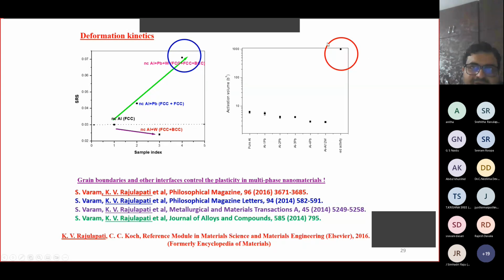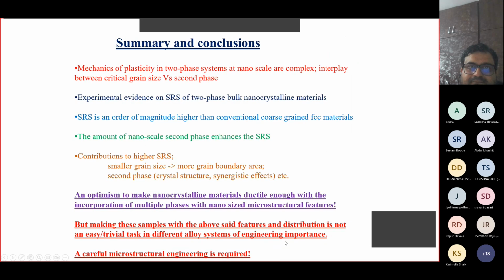And the activation volume for conventional metals is 1000 b cubed, where forest dislocations play a major role in governing the mechanics of plasticity. But here you see that it's always below 10 b cubed. b is the Burgers vector. And that shows that the grain boundaries and other interfaces play a major role in nanostructured materials to govern the mechanics of plasticity. And we also mentioned all these details in an encyclopedia article that we published in 2016.